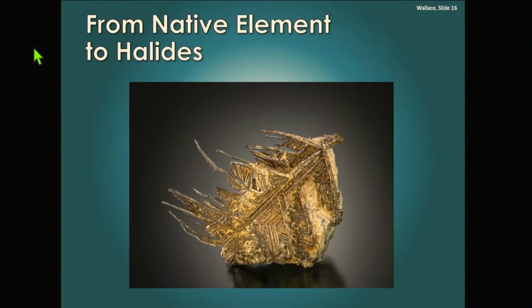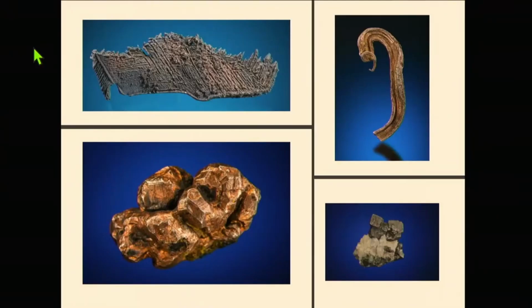Peru. And what you see is crystals of silver which are growing as octahedrons, but they're twinning such that you get this herringbone pattern. So this would be a natural crystal that you would expect for silver. If I look at all the rest, typical silver, there's another herringbone on the top. That's from Chanarcillo. That's about 10 inches across. So it's a pretty spectacular silver plate, but it's the same herringbone pattern.